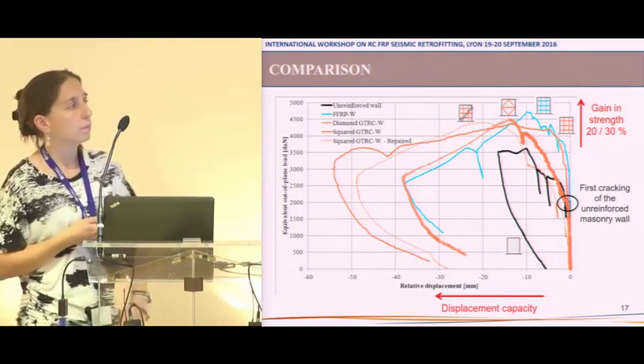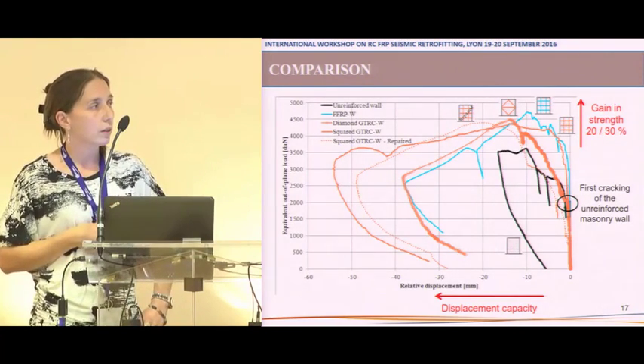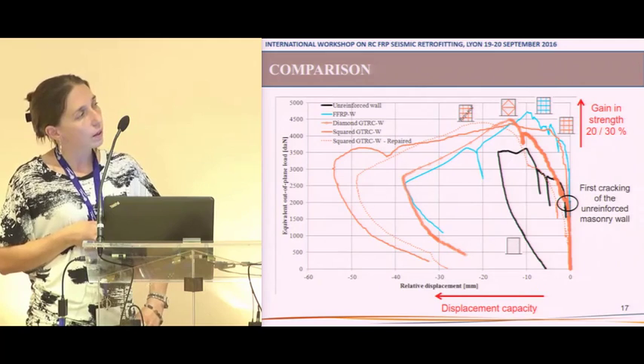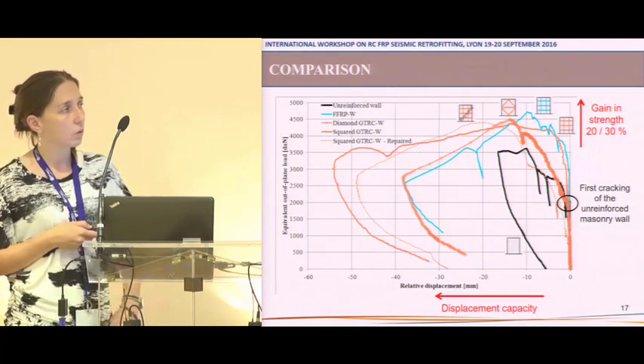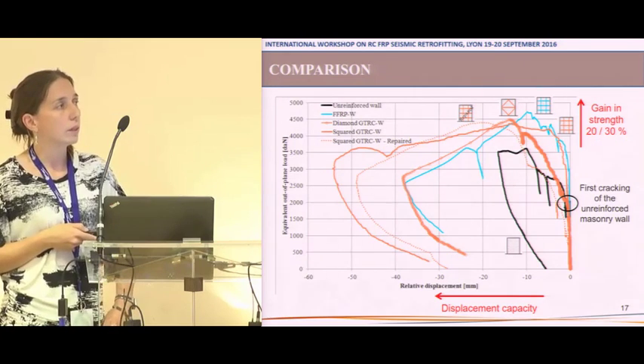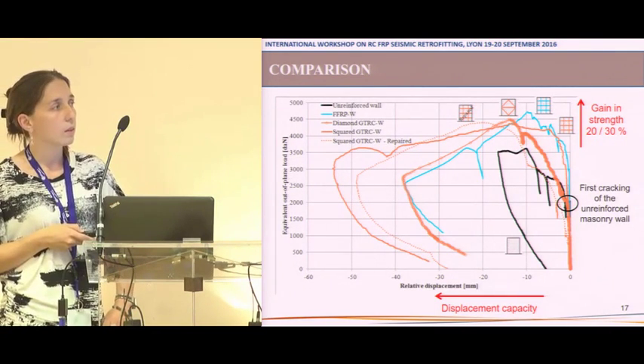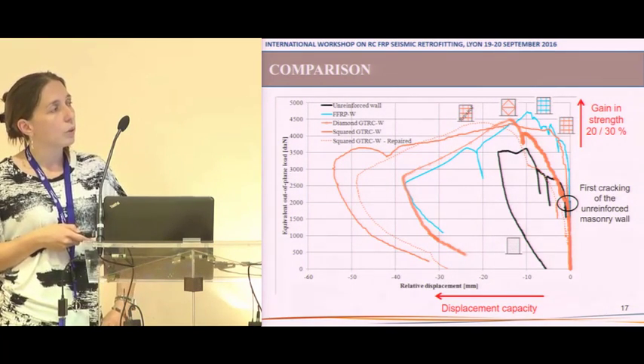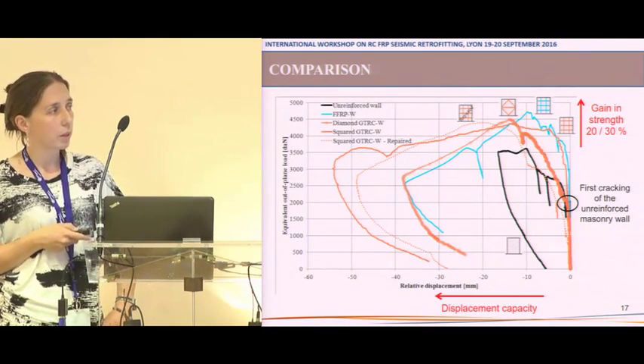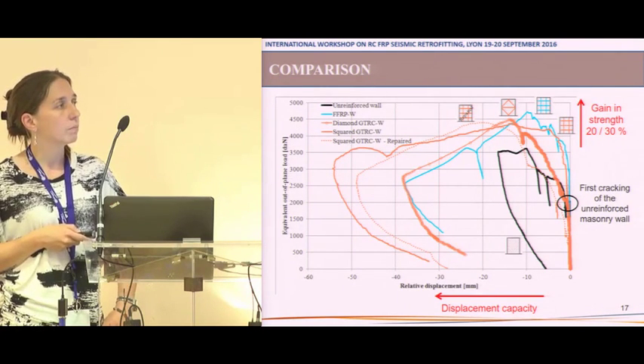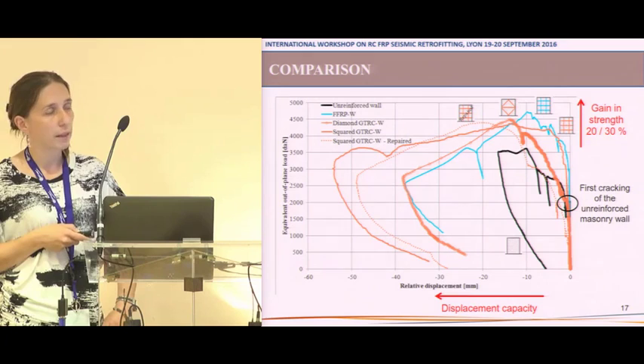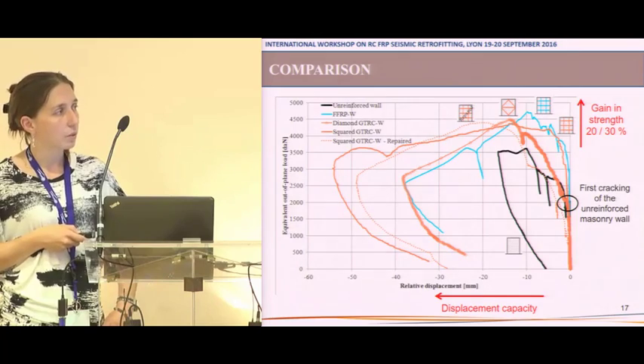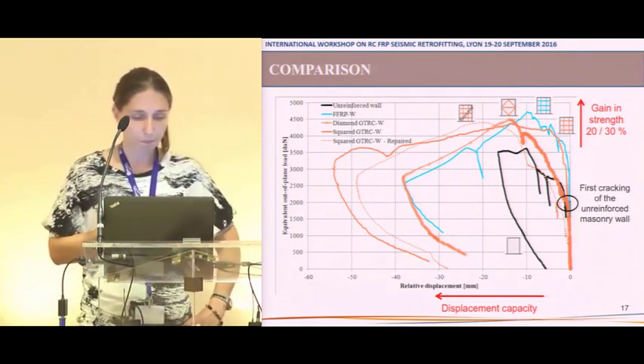If we compare all the walls, we can see that the reinforced or repaired configurations enable an increase in the lateral strength, and the gain is about 20 to 30%. We also see that no configuration experiences a sudden drop in the load when reaching the maximum, and they all present some ductility and displacement capacity after passing the maximum load.